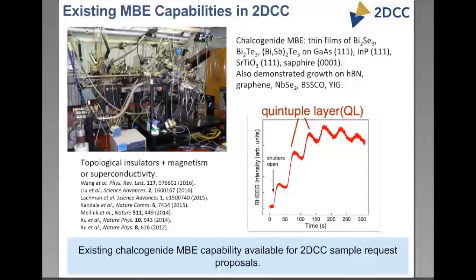and antimony chalcogenides. So we've grown chalcogenide thin films on a variety of substrates such as gallium arsenide, indium phosphide, STO, sapphire, and so on, as well as a host of other types of substrates. And a big interest of ours at Penn State is combining these topological insulators with magnetism and superconductivity. So I just want to advertise that as part of the 2DCC, until our new chambers are set up for growing transition metal dichalcogenides by MBE, our current emphasis is in satisfying sample request proposals.